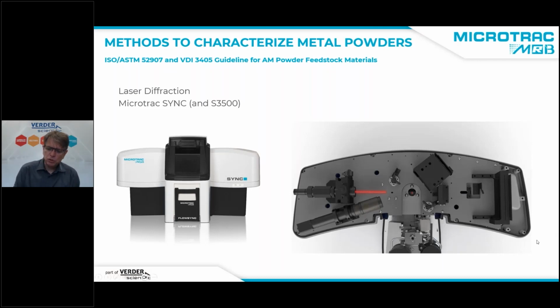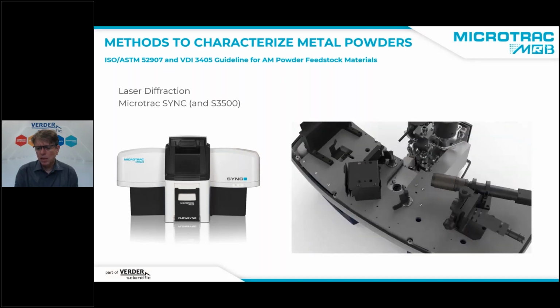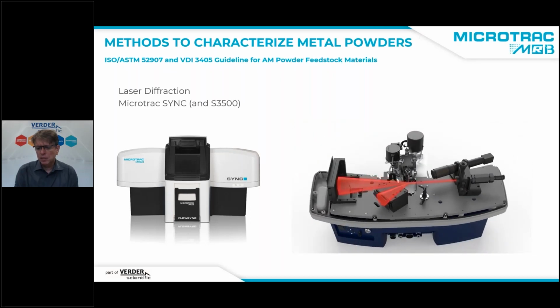Both instruments feature the same laser setup. So we have laser light which shines on the sample. At the sample, the light is scattered. We are using 3 lasers from 3 different directions which scatter the light on 2 detectors. And in addition, the camera allows us to measure the particles in images. So we can see images and scattering pattern, and we can calculate laser diffraction results and imaging results at the same time. So this is a very unique combination which is not available in any other instrument.